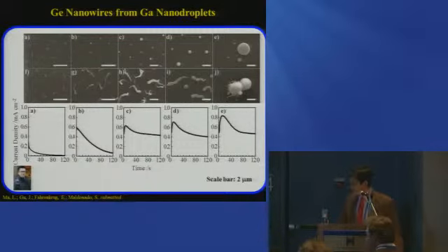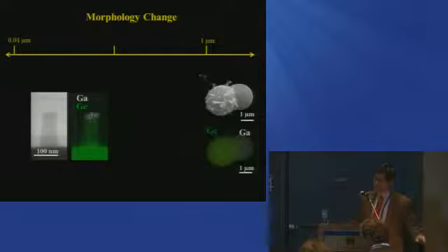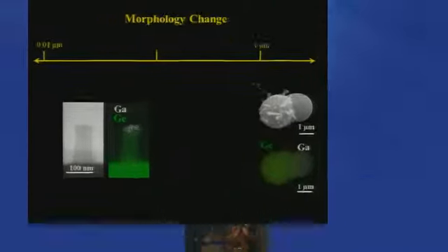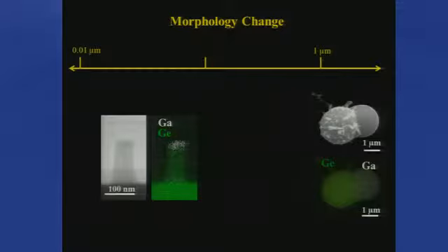Yeah, well, there's a size dependence, it turns out. It's a function of several different things, but in some cases, we see that for small micro or nano droplets, you get the formation that favors this one-dimensional needle or nanowire. When you make that gallium blob large enough, eventually you transition to a macroscopic domain where your crystal starts to become basically isotropic. I think what happens is that when it becomes large enough, nucleation becomes homogeneous, and now you start growing a crystal in all dimensions. Here, there's something that preferentially directs crystal growth, be it the size or the substrate that you're growing off of. I don't know if this is a universal transition, but we do see this effect where size matters.